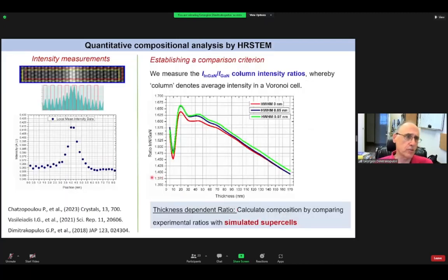So if you have all this information, what you do is you do intensity measurements. Of course, we are showing this in a rough way, because in reality, you are using the Voronoi tessellation of your image. You have separated your image in Voronoi cells. So you are taking the intensity, say, of multiple such cells. And if you have an area where you have different intensity, then you need to compare it with a reference area where you know the composition. For example, here is gallium nitride, and this is a quantum well, a very thin one, which is indium gallium nitride. So you measure the ratio, how much brighter this area is compared to the reference area. So you make a column intensity ratio.